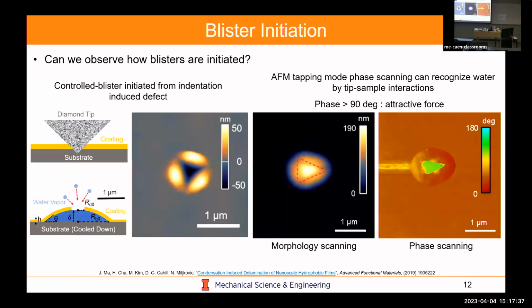By using things like diamond tip nanoindentation, we could then also study things like how does the shape of the pinhole and the size of the pinhole affect the blistering formation process. And so the model we have is that there's this pinhole that forms, water has access, it nucleates on the substrate itself because of the high surface energy. And then as the water propagates, it delaminates the coating and forces it to actually come off the substrate. And so you could actually see this in situ.